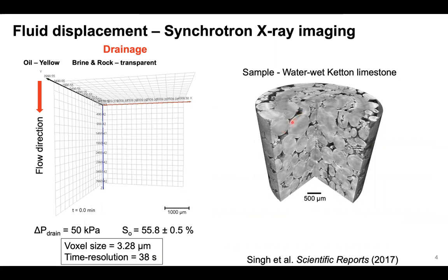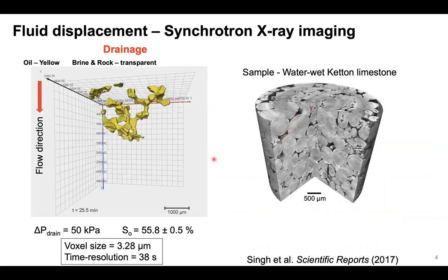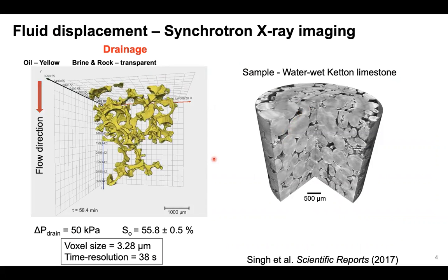Here, what you see is a pore space, and these are the rock grains. It has microporosity. It has some complexity in this. So with the experiment, we fill this initially with water, and then we inject a non-wetting phase. In this case, we use oil to displace this water. This process, which is called drainage, you can see we see big jumps here and there. This is a typical characteristic of a drainage process, which is mostly controlled by throat sizes.